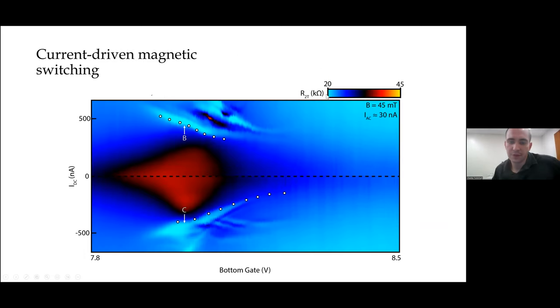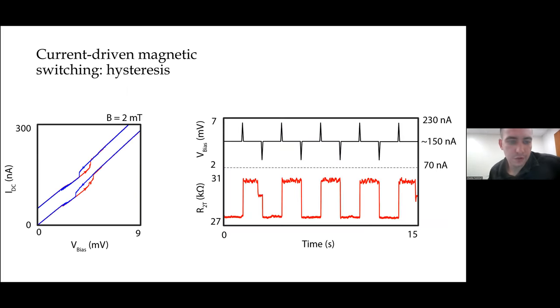We can overlay that with the transport data, and we see that the transport data is closely associated with this local magnetic switching phenomenon. This is also something that we can see in the DC data, and indeed, it is a first-order phase transition. So what's going on is there is a magnetic domain that is being nucleated by DC current in this regime on one side of the device transverse to the applied current. And this is something that we can flip controllably with excursions in DC current.